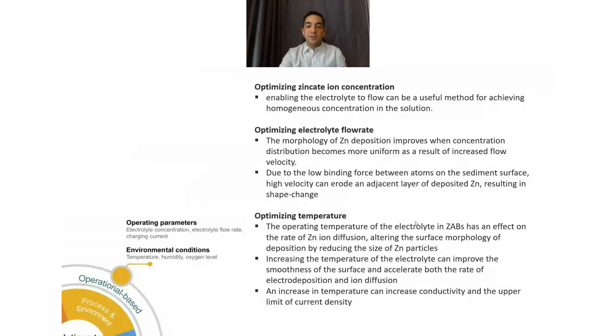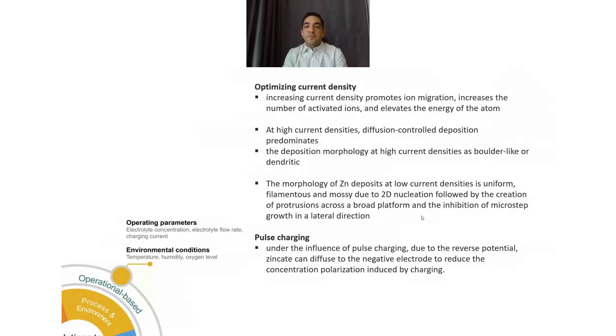The high temperature will also increase the kinetics of zinc and affect the morphology. And the last one is the current density. So increasing current density promotes ion migration, increases the number of activated ions, and elevates the energy of an atom. At high current densities, diffusion control deposition predominates. The deposition morphology at high current density is boulder-like or dendritic.